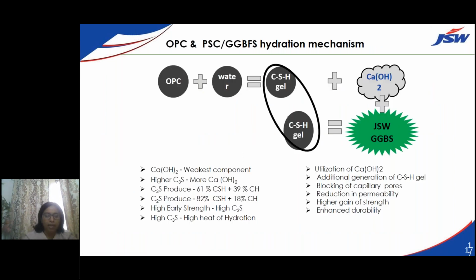So what is the hydration mechanism which is happening? When OPC is mixed with water, there is a calcium silicate hydrate gel which is formed, and calcium hydroxide is also formed, which is a byproduct. So this calcium hydroxide, normally what it does, it goes and occupies the space which is very near to the aggregates, because those spaces are spaces where there are a lot of pores and voids. The water which is there inside slowly gets evaporated, and the water interacts with the cement, and the calcium hydroxide goes and takes those places.